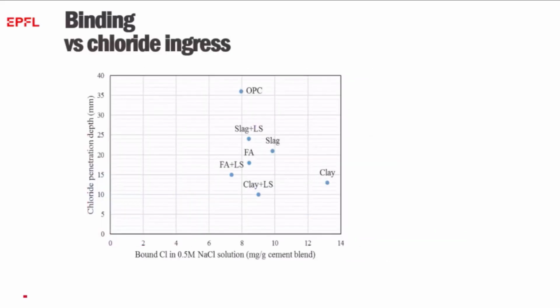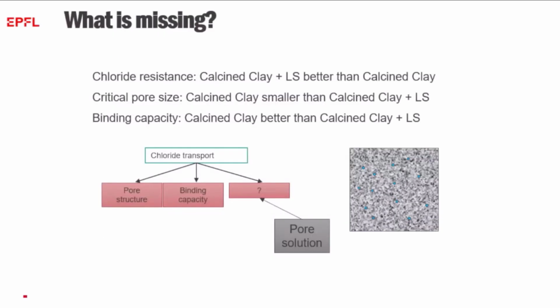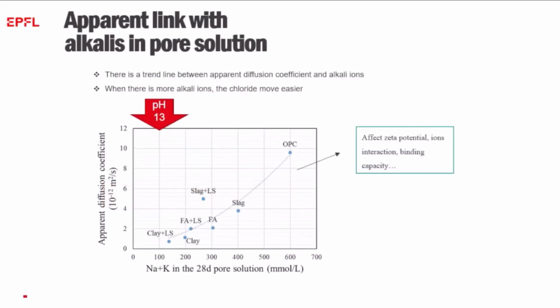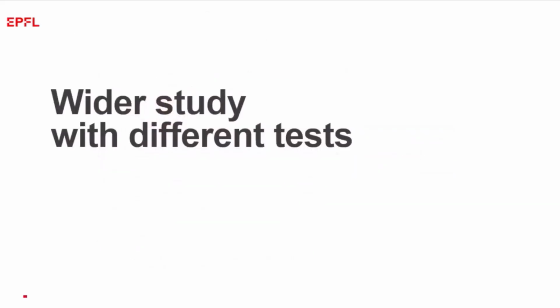And this is the overall correlation. Again, you can see no particular interest. And so we got something missing. Well, what's probably missing is the concentration of the pore solution. We can see there's a very nice correlation between apparent diffusion coefficient and the sodium potassium in the pore solution. And I would like to point out that even though we lower the sodium potassium in the pore solution, we're still well above pH 13, so no problem for protection of reinforcement.